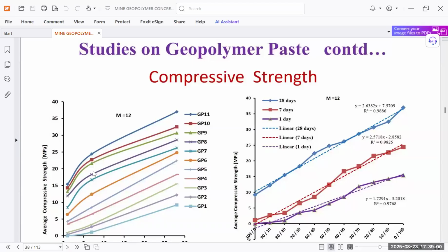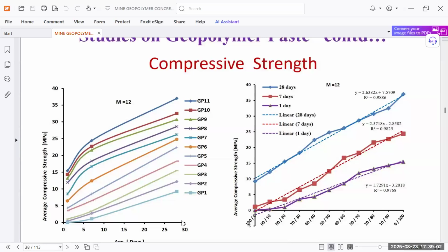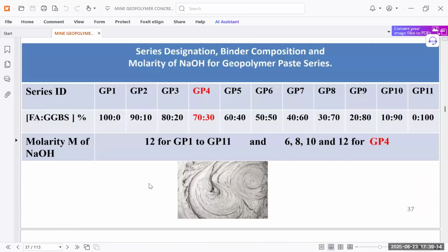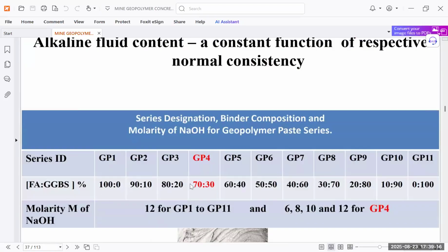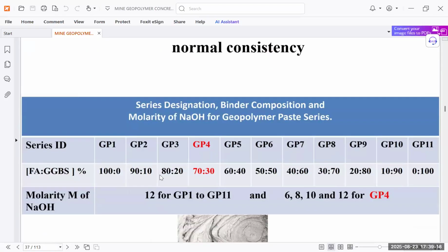So as per the strength for different days, you can see that after 28 days strength, we can see that different for this fixed molarity of 12, the change of this graph has been put, so we can achieve the required strength. Whatever strength we are having, these mix proportion ratios we can take care of, so that our required strength of the concrete is obtained.